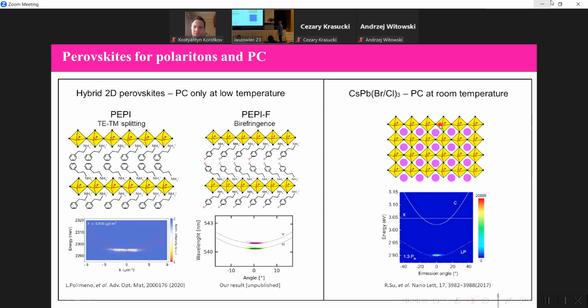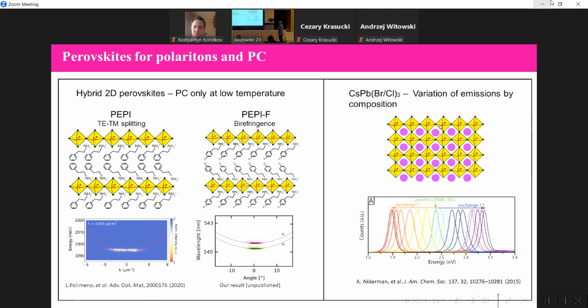You can't exfoliate this thing. But what's very nice is there's variation of emission - if we change the composition of this material, we can have the maximum of emission at different wavelengths, from red to purple. Not every type can host condensation, mostly the chloride and bromide and mixtures of these two elements. In iodine, it's very tricky to obtain condensation.